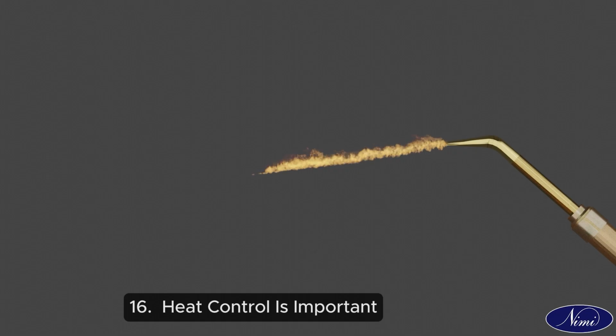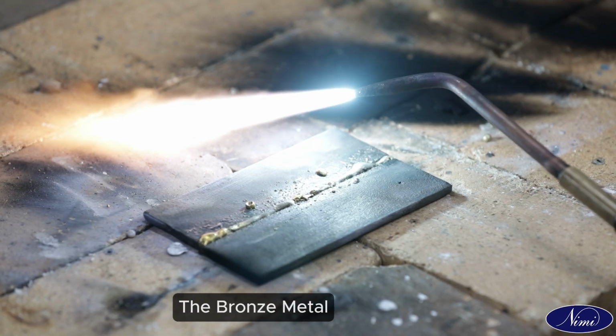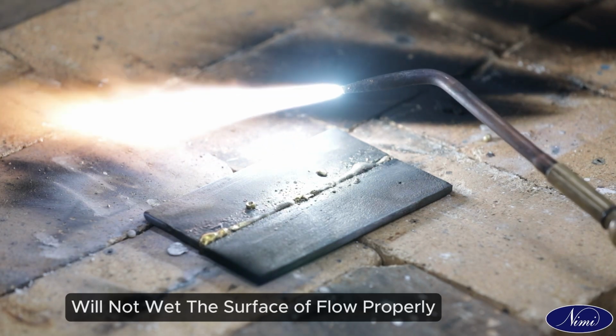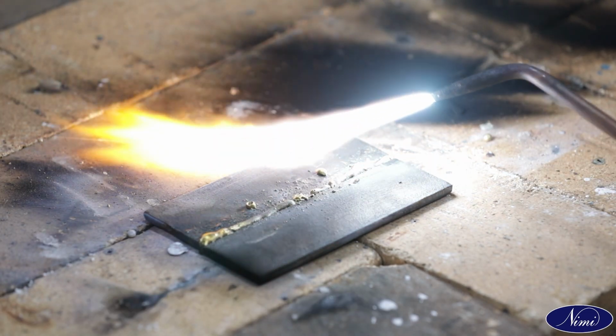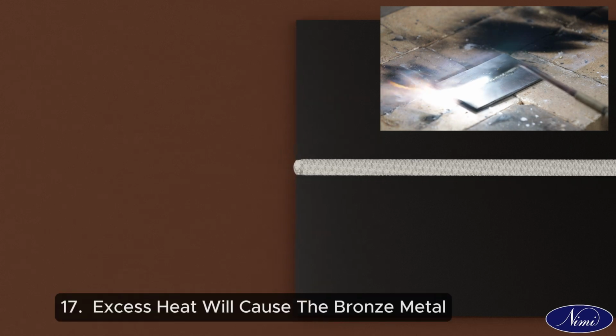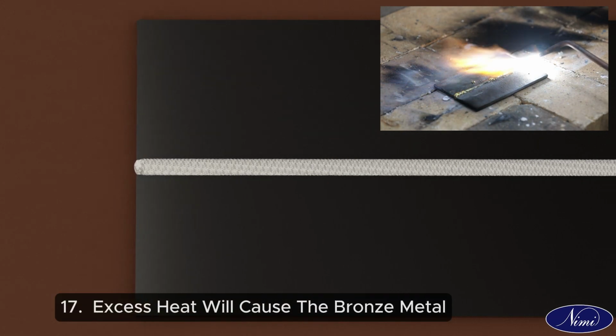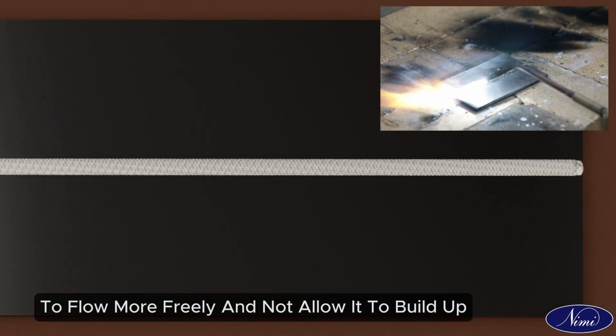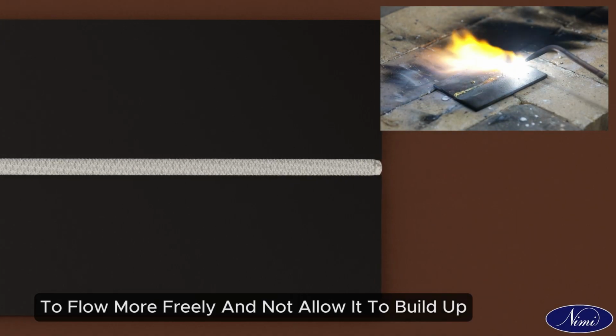16. Heat control is important. If the heat is insufficient, the bronze metal will not wet the surface or flow properly. 17. Excess heat will cause the bronze metal to flow too freely and not allow it to build up.